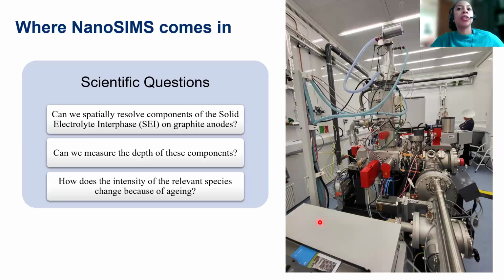So the scientific questions I wanted to address using the NanoSIMS and lithium-ion batteries are, number one, can we spatially resolve the components of the SEI on graphite anodes in particular? Can we measure the depth of these components? And I will use the term depth very loosely because we don't have a quantitative depth. We just know how the intensity of the components varies as we go through the successive surface layers. And how does the intensity of the relevant species change because of the aging that we see?